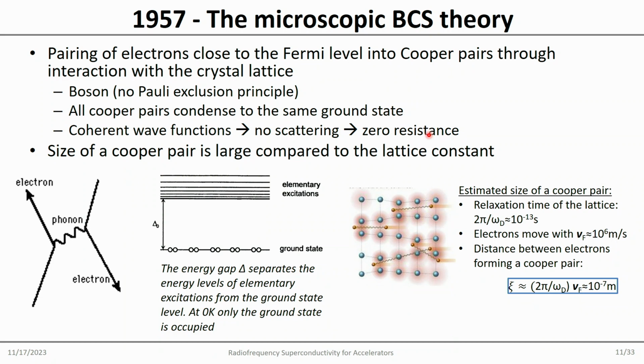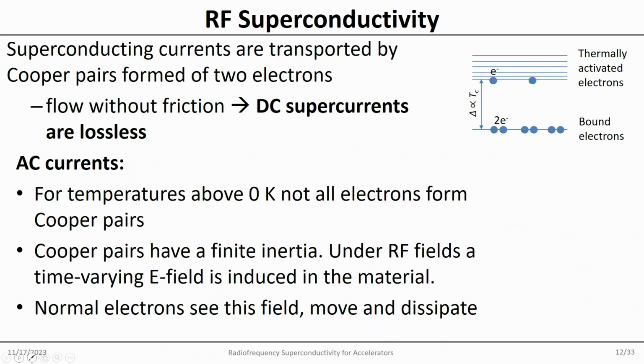We said that there was a coherence, and we thought, what is the size of the Cooper pair? How far do they interact with each other? You can make a rough estimate for that. This is not 100% correct, but it gives the right order of magnitude. If you just think about the relaxation time of the lattice and compare that with the Fermi velocity, which the electron moves at, you get about 100 nanometers. This is really what the coherence length is: how far these electrons can communicate with each other and form a Cooper pair. Okay, so far everything was about DC superconductivity.